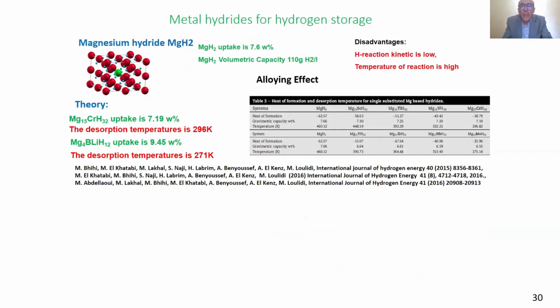Okay, I give briefly some results concerning this material, and I go to 2D material based on magnesium hydride. Magnesium hydride has an uptake of 7.6 weight percent, a very good value compared to the norm, which is less than 6. And the volumetric capacity is very good, 110 grams of hydrogen per liter, higher than the norm.